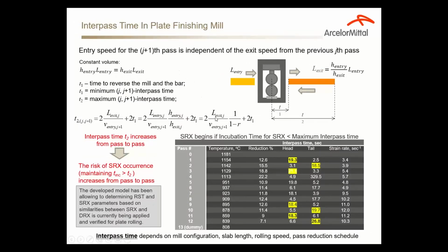And the same applies to interpass recrystallization, because in plate rolling and reversible rolling, interpass time increases from pass to pass because the length of the strip or the plate increases as it's being rolled. And we are talking of much longer interpass times compared to those in hot strip rolling. So for plate rolling, static recrystallization control becomes very important.